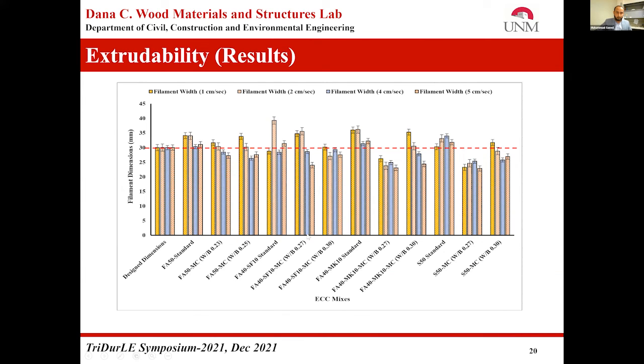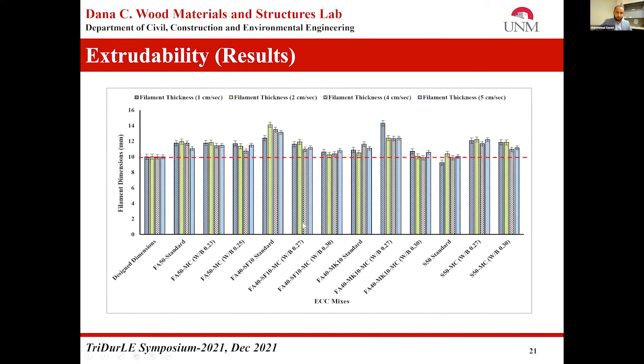The printability trials show the extrudability of the mixes when we compare the methyl cellulose enriched mixes with the standard ECC mixes. The mixes with the addition of viscosity modifying admixtures show less variability when we compare the dimensions of the filament with the design dimensions in terms of width and thickness.